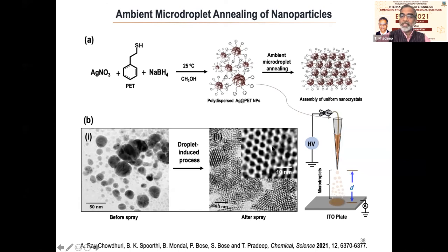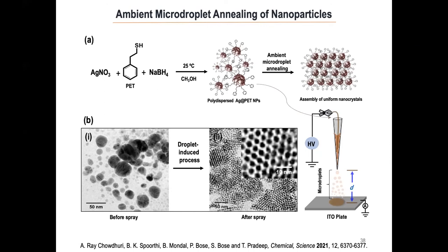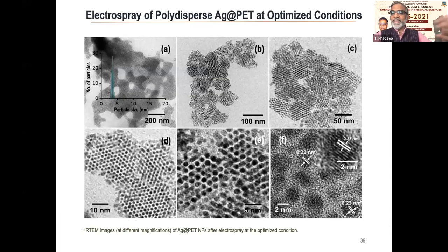There is another methodology. Such polydispersed particles, if you anneal at a high temperature in solution for a week, you can get monodispersed particles. So essentially, you are doing all of these processes so fast in ambient electrospray. Now, this is not just some region. We take a large area, and this electrospray is happening over a reasonably large area that we can image. Very monodispersed, expanded, further expanded, you see that this is what happens to particles.